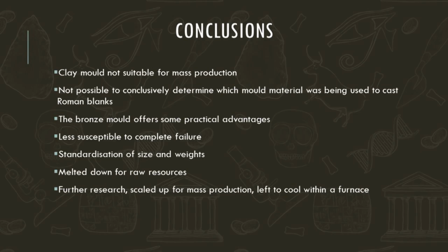So finally, the conclusions. From the current information, it's not possible to conclusively determine which mould material was being used to cast Roman blanks. However, the bronze mould offered some practical advantages over the other 2 materials. The bronze mould was less susceptible to complete failure compared with the clay, and it can be reused many times. The standardisation also achieved using the bronze mould was quite striking. In addition, any moulds made from bronze would be melted down for the raw materials following use. This is actually a good explanation as to why no Roman flan moulds have been found in the archaeological record.